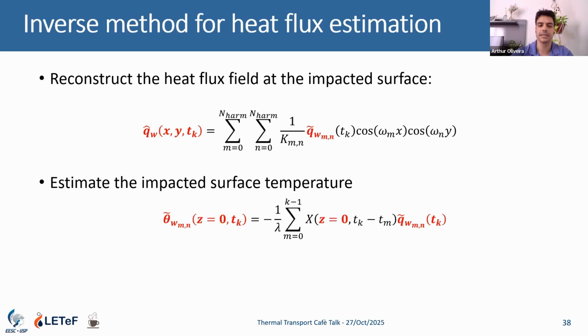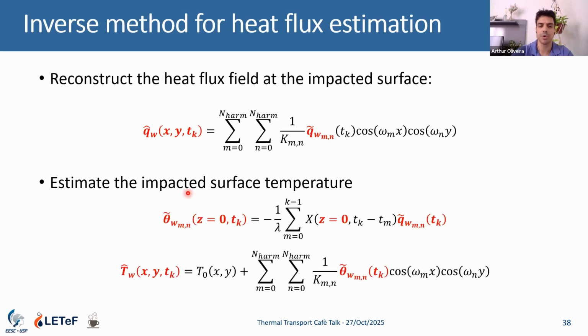And we can also estimate the temperature of the plate by solving the direct problem using the estimated heat flux. So we estimate the temperature harmonics and finally the temperature field during the droplet impact. Because with a metallic plate, we are measuring the back surface temperature, but I'm interested in the impacted surface temperature. So that's what we are estimating with this equation.